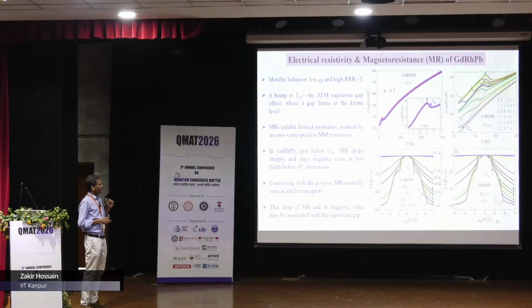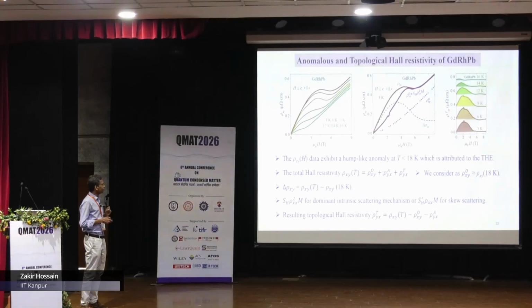Like previously we did resistivity and magnetoresistance, but I will come to the particularly interesting feature of this compound, which is the topological Hall effect. For the Hall effect, like in the previous cerium compound, we could fit with two terms only, rho naught B plus something with magnetization. Here we tried that and could not succeed. So we need some additional term, which we attribute to this last term. We call it topological Hall effect.